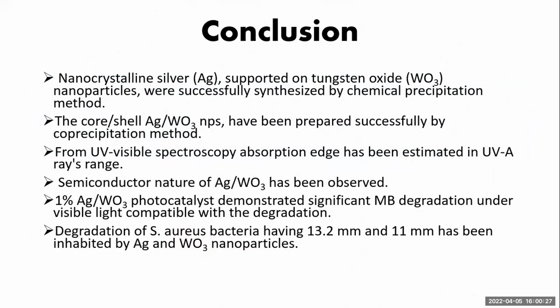After that we reach the conclusion. Nanocrystalline silver supported on tungsten oxide WO3 nanoparticles were successfully synthesized by the chemical precipitation method. The core shell AgWO3 nanoparticles have been prepared successfully by the co-precipitation method, and from UV visible spectroscopy, absorption has been estimated in the UVA range, and the semiconductor nature of AgWO3 has been observed. 1% AgWO3 photocatalysts demonstrate significant methylene blue degradation, compatible with visible light.